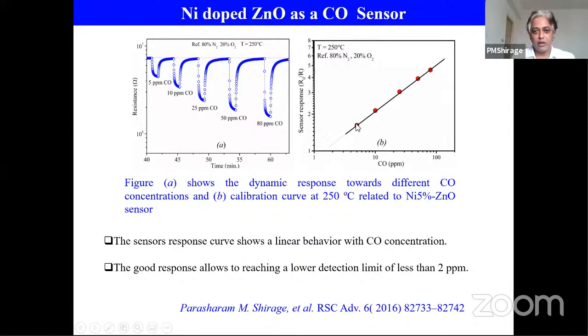Okay, and by using this sensor, we can detect a minimum of 2 parts per million. It is a very small amount of CO present in the atmosphere that we can easily detect with this. So if we use this nickel doped zinc oxide, then we can make a very good CO sensor. I'm showing only the highlighted part; there's selectivity and other things that I am not talking about.